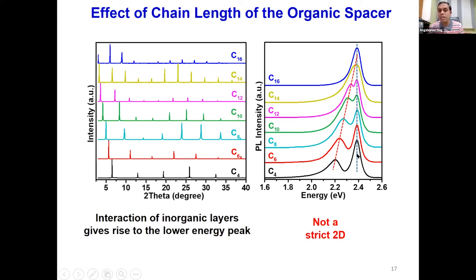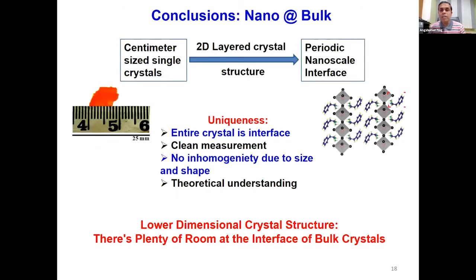It looks like the high energy emission comes from the isolated inorganic layer. And then as the carbon chain length increases, the interlayer distance increases, so the interaction between the inorganic layers decreases. And that's why you see this shift in the lower energy emission. This further supports our hypothesis that probably there is some kind of interaction between the inorganic layers. Now with this, I come to the conclusion slides.